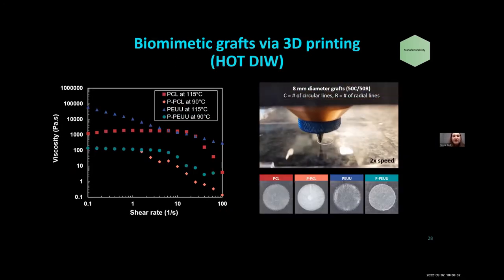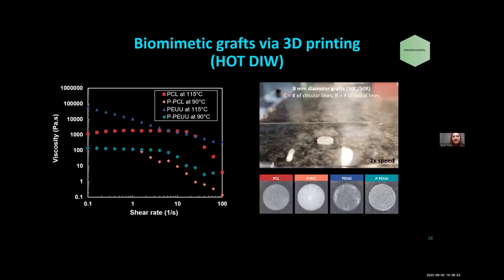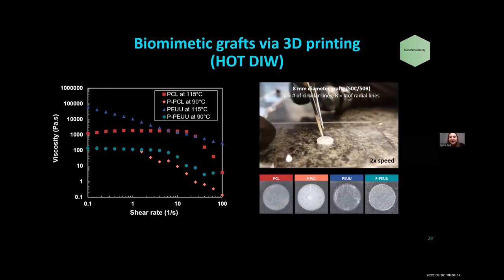And so we're able to create these inks ultimately that have these really cool shear thinning properties as well, which essentially means as the shear rate on these materials increases, their viscosity decreases. And so essentially trying to squeeze this material out of a small nozzle, you can get it to be deposited. And so this is one of the polyurethane inks being printed from a custom hot direct ink write setup we have. And so we're able to create these four inks that can be patterned into these circular and radial architectures at high resolution.